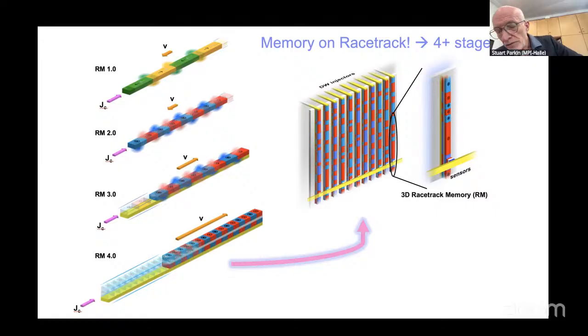energy. So alternatively, you could make a form of racetrack from a perpendicularly magnetized material. This is racetrack memory 2.0, where now the domain walls are made much narrower by introducing a perpendicular magnetic anisotropy, typically by forming the racetrack magnetic material from alternating layers of distinct materials, e.g. cobalt and nickel. When these are atomically thin, the interfaces break symmetry and give rise to large perpendicular magnetic anisotropies. This was extensively studied in the 1990s. So this shrinks the domain wall width by 100 times.